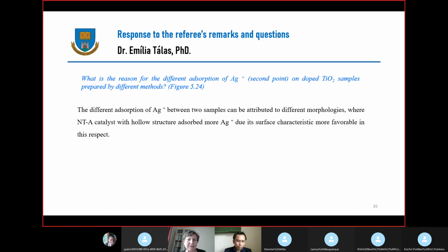I understand, but it was interesting that when you finished the whole procedure, the total silver content was very similar. Oh yeah, because the concentration of the silver was very small. So after UV radiation, all the silver content was maybe deposited on the surface of the catalyst, because compared to the catalyst, its concentration is very small. Yeah, so it means we have to imagine this process: the first step is adsorption, after that there is a reduction, and again reduction because of the UV light.